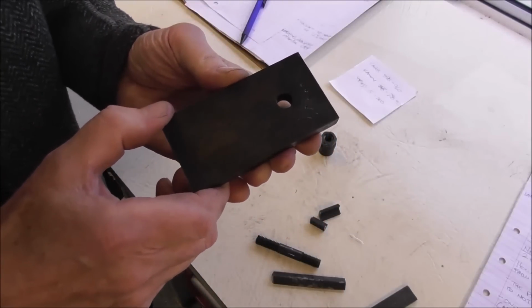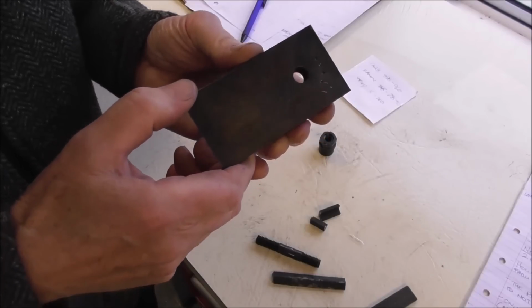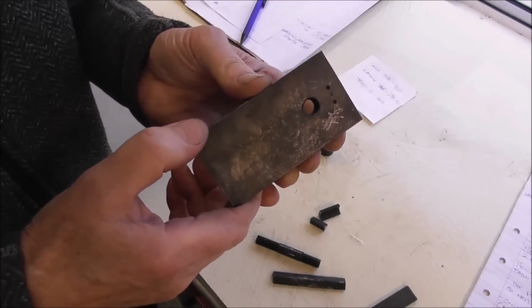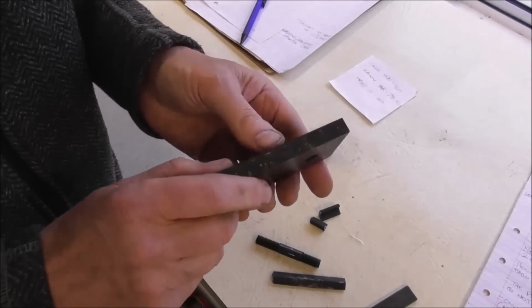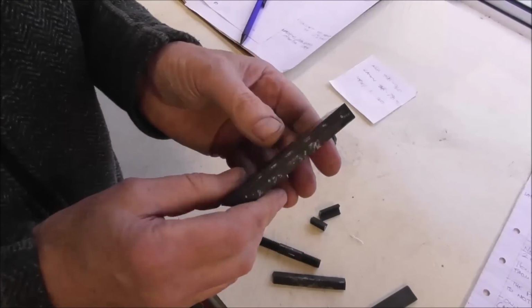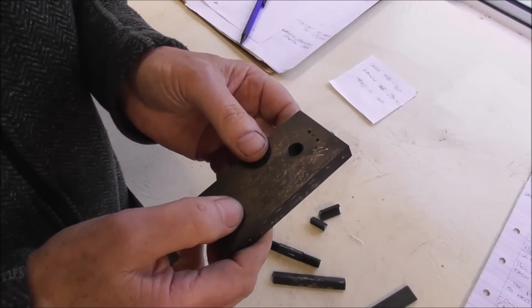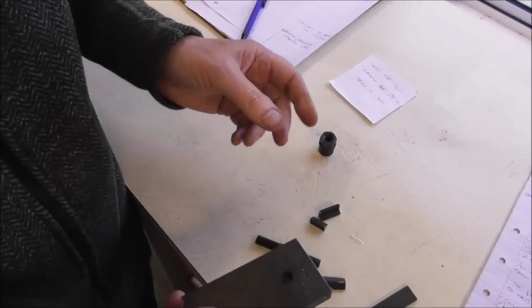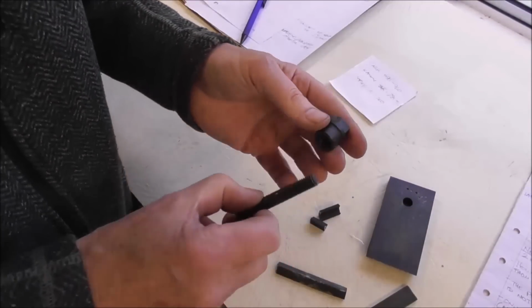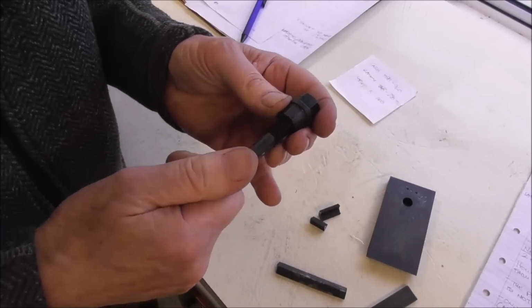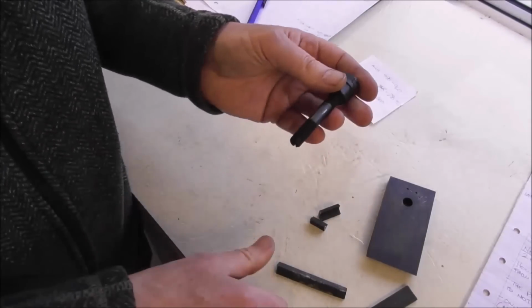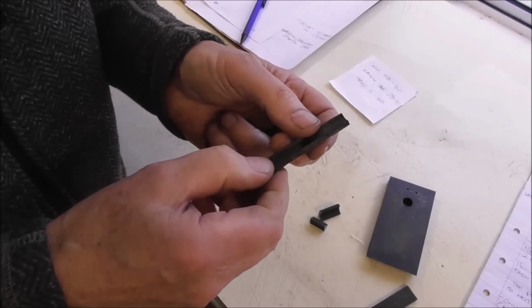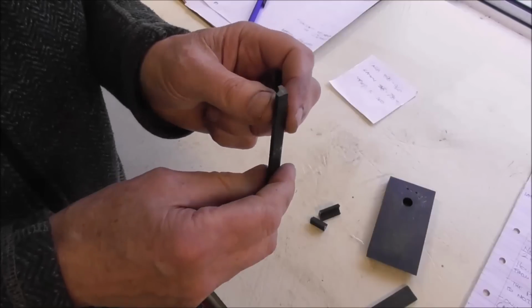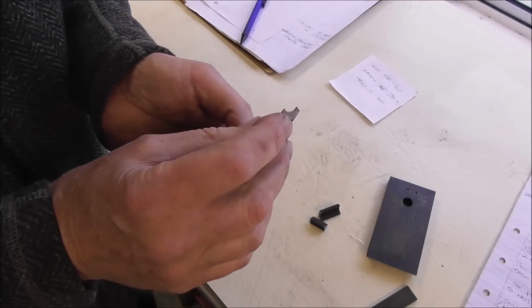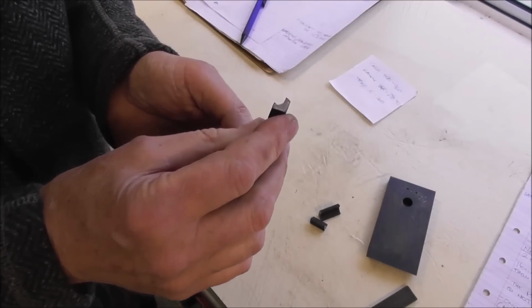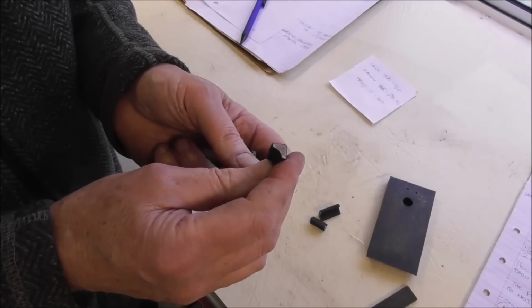I'm a bit mystified by that. 200 degrees C shouldn't really have softened it that much, but it seems to have in the case of this steel. Of course, I don't know the exact makeup of the steel, but it looks like I've got quite a bit to learn still about case hardening. These parts are still hard and have behaved as expected. This mild steel piece here has hardened right through. That surprises me. It's definitely mild steel, but why did it harden right through after only 4 hours?